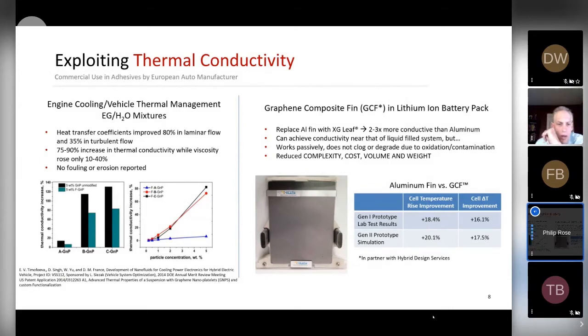On this slide are two other examples exploiting the thermal performance of graphene nanoplatelets, but neither of these are commercially in use today. On the left are data for use of various graphene nanoplatelets at 5 weight percent in ethylene glycol and water-based engine cooling systems. The data show heat transfer coefficients improving 80% for laminar flow and 35% for turbulent flow, translating into from 75 to 90% improvement in thermal conductivity and with a low impact in viscosity.